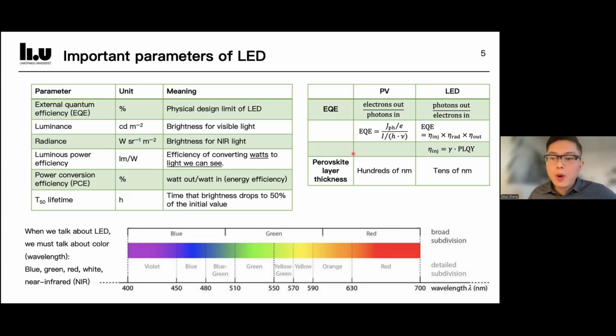I also include a small table to compare how EQE is defined in LEDs and PVs because they are quite different. So in PVs, EQE means electrons out per photon in, but in LEDs, it means photons out per electron in. The same term, but very different perspective. One more important thing is that the thickness of the perovskite layer is very different in LEDs and PVs. Normally, it is hundreds of nanometers in PVs, but tens of nanometers in LEDs. And this could cause a large difference in material impacts.